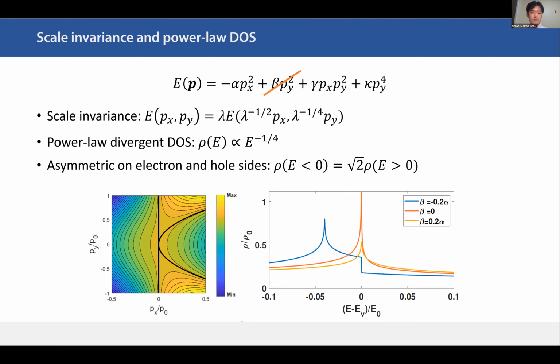And this has another interesting feature, which is an asymmetry of the density of states on the electron and hole sides. The usual log divergence accompanying the saddle point in 2 dimensions has a symmetric divergence of density of states on both electron and hole sides. But for this high order Van Hove singularity, we can see asymmetry of the density of states on the electron and hole sides.